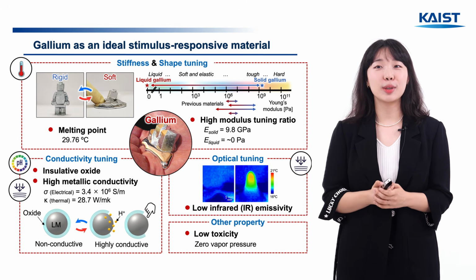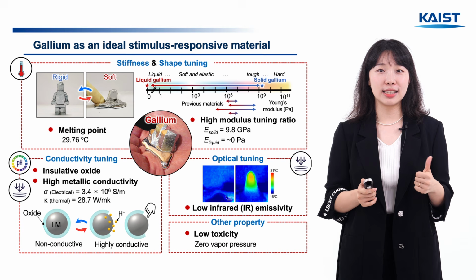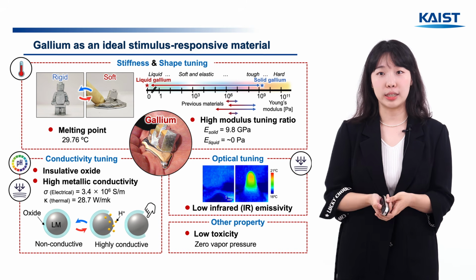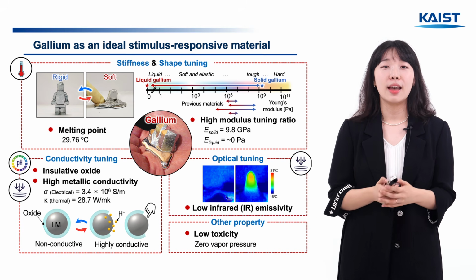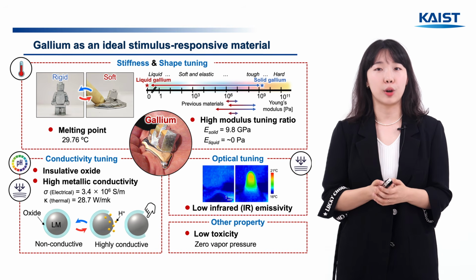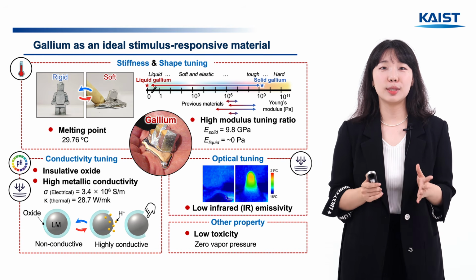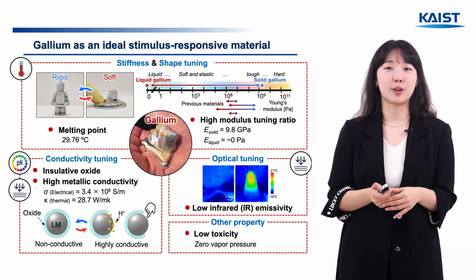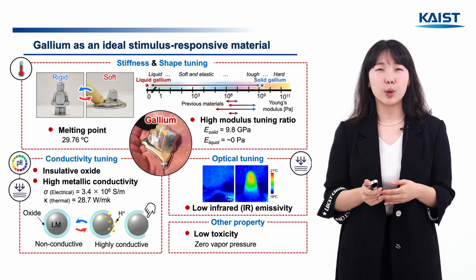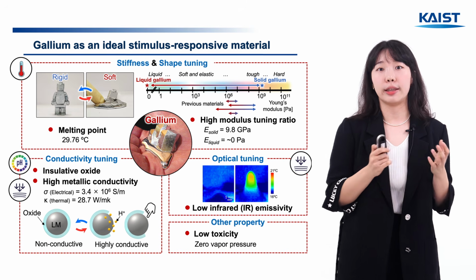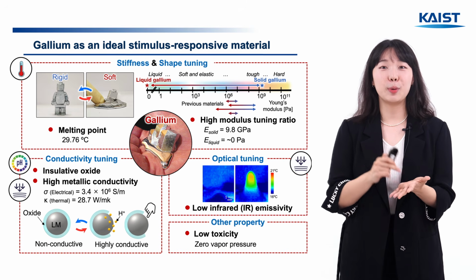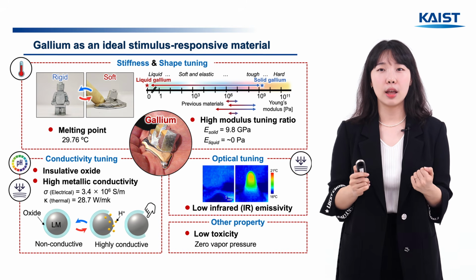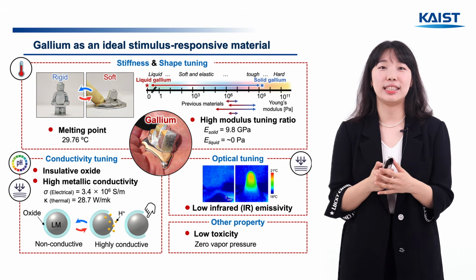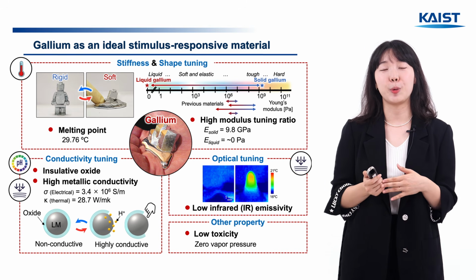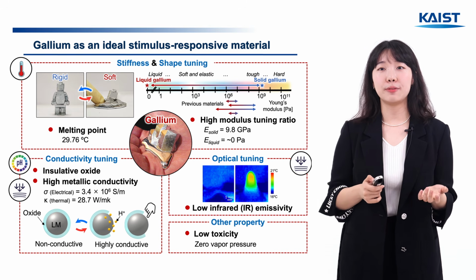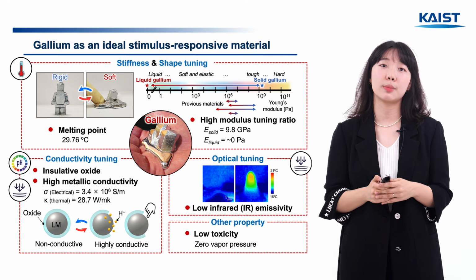To start with, gallium can tune various properties: stiffness, conductivity, and even optical properties, all in a single material. And the range it covers for each one is remarkably wide. In terms of stiffness, around its melting point of about 30 degrees, gallium goes through a phase change. In a solid state, it's 9.8 gigapascals, as hard as a metal, and in the liquid state, its stiffness drops close to zero. That's a billion-fold change in stiffness, which was not achievable with previous materials.